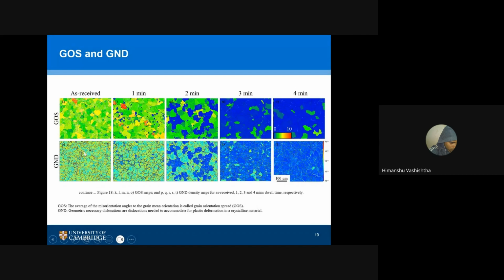It's recovering. For the geometrically necessary dislocations, the scale is from 10 to the power 12 to 10 to the power 16. You can see with heating it follows the same pattern as GOS. This GND has been calculated using MATLAB, and the remaining things calculated using some commercially available software.